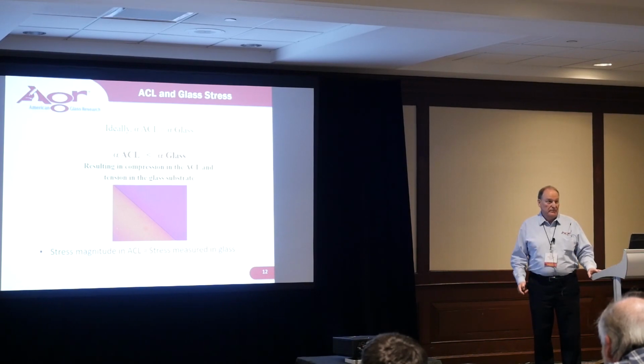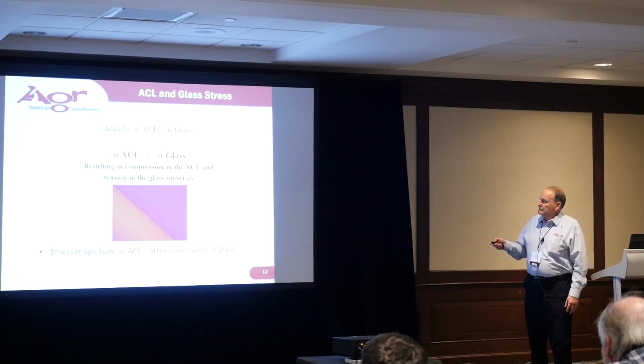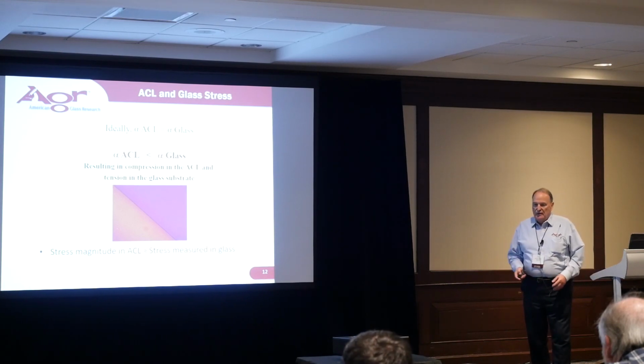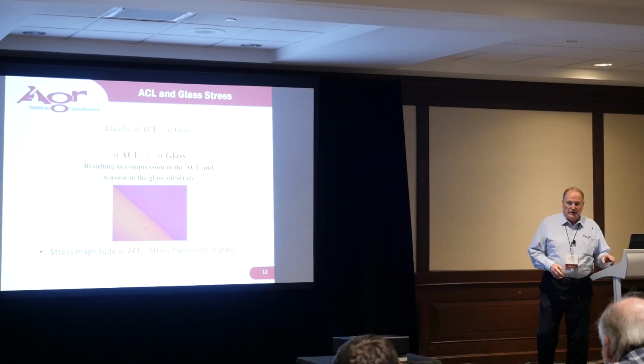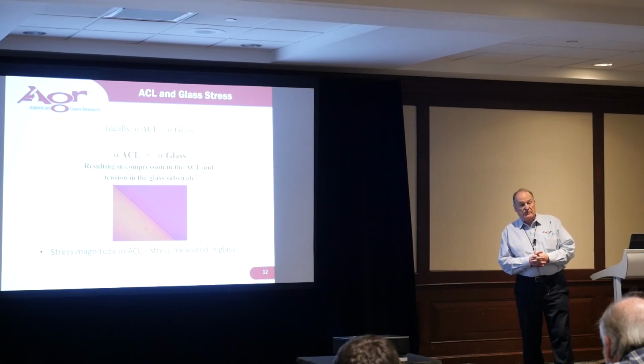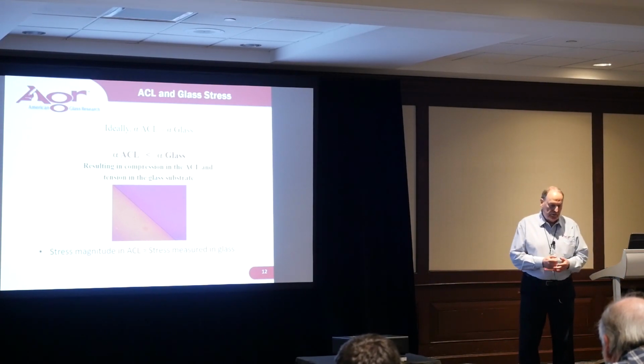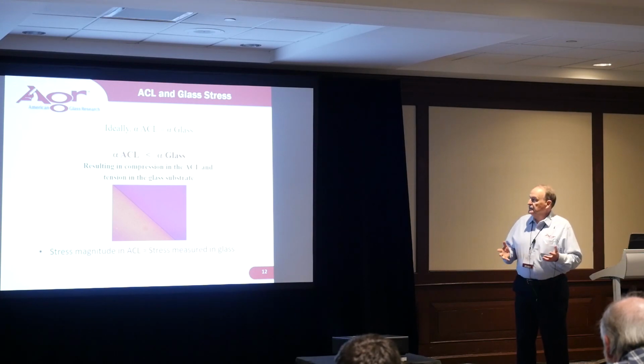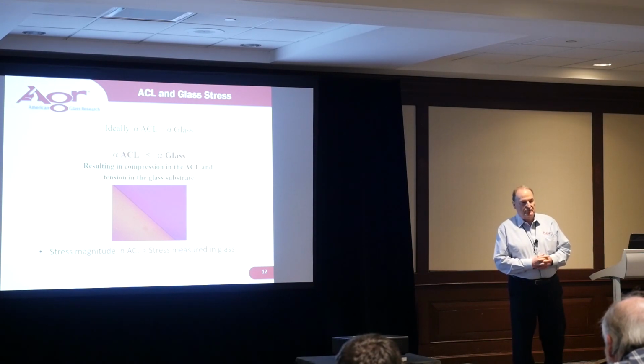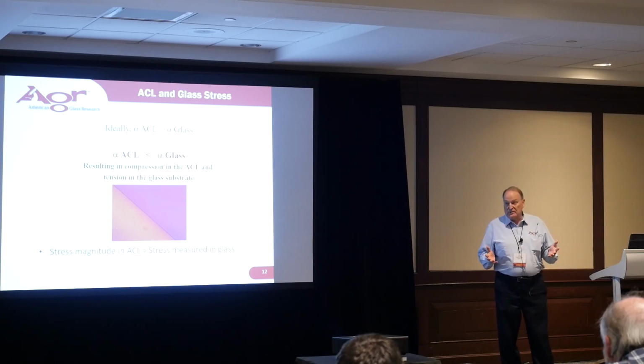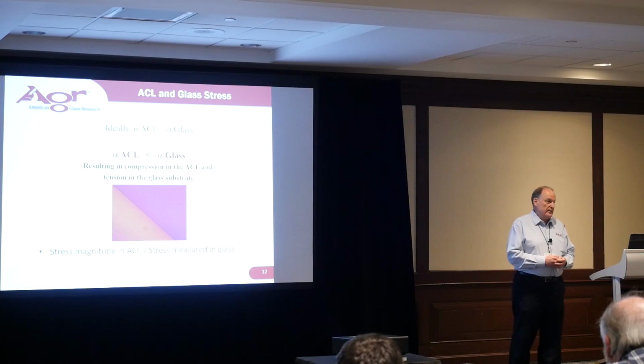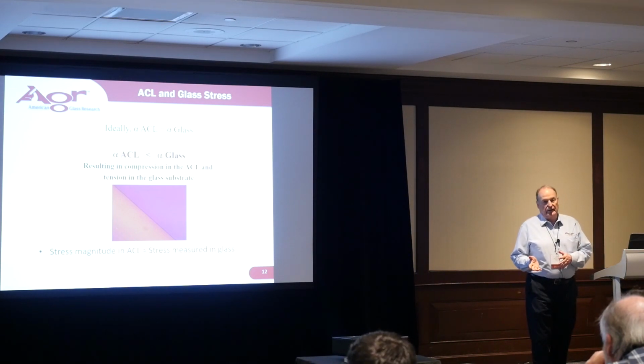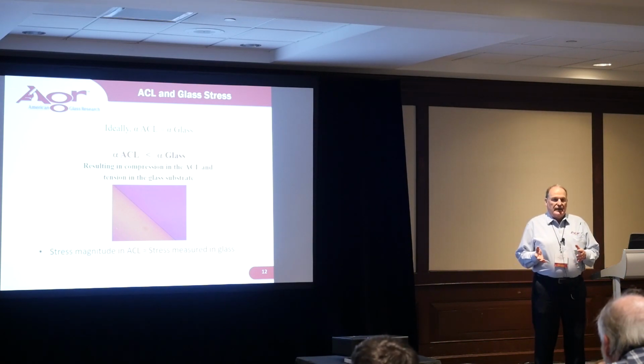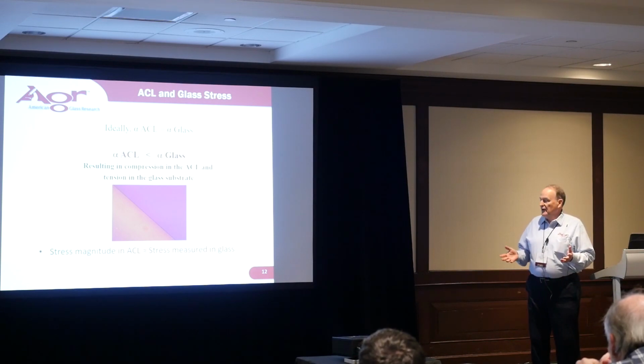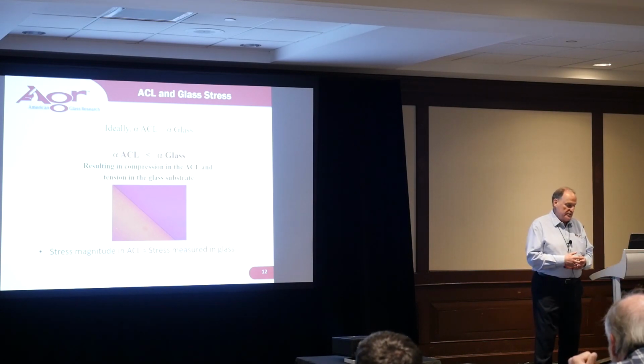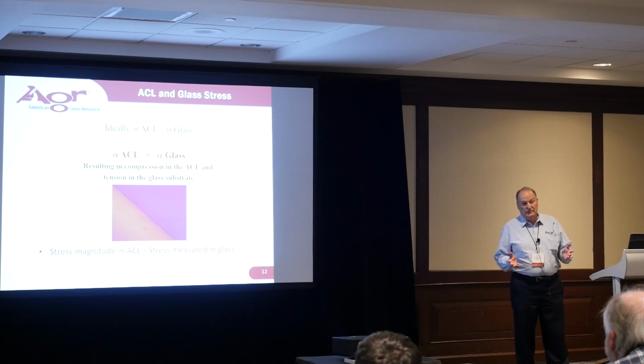We have no idea. Now, ideally, you would like to choose your label material such that the coefficient of expansion of the ceramic label, once it's fired on the glass surface, equals that of the glass. In those situations, there will be no stresses generated in either the label or the underlying glass substrate. In practical terms, this is very hard to achieve. I would even go as far as to say probably impossible.